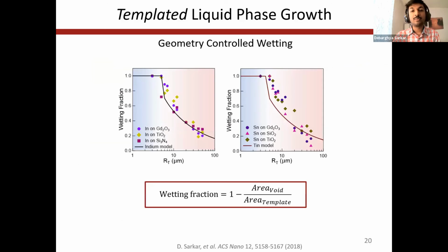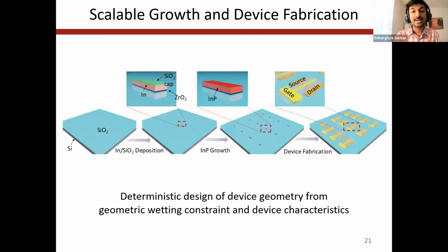This is a comparison of the thermodynamic model with the experimental data for both indium and tin and on different substrates. The very good quantitative match indicates that the model is quite robust and reliable in predicting the wetting propensity of different liquid metals and on different substrates, so that we can utilize this knowledge to deterministically design different device geometries, grow them accordingly, and scalably fabricate devices with a knowledge of the substrate surface energy and the device intended characteristics.